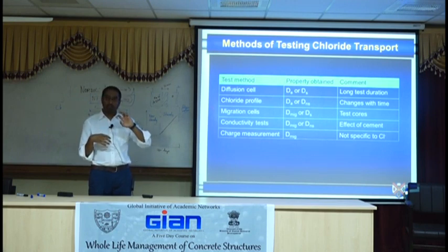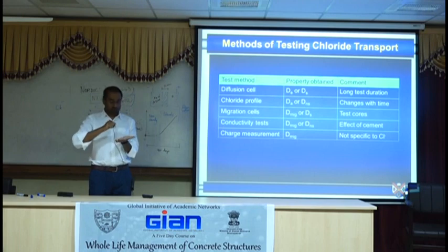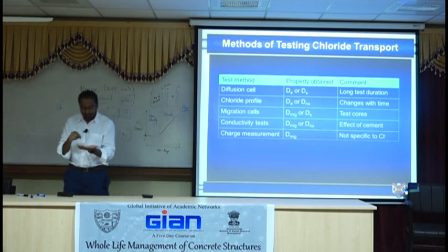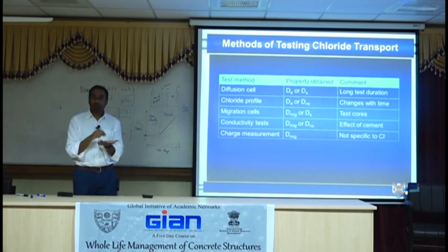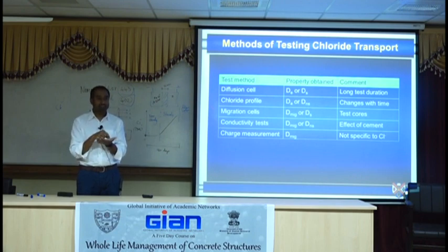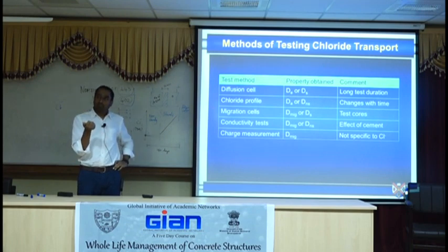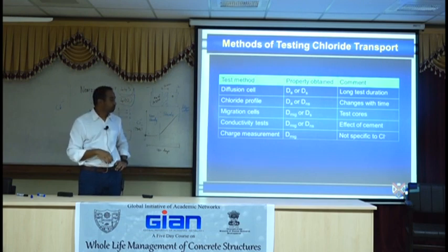Silver nitrate is a very fast oxidizing chemical. Be very careful when you're using your hand with it. It's the same stuff that you have in henna, you know, the drawings that you guys make. Most of the commercial ones that you buy, which is not really henna, actually has silver nitrate in it. It gives you an etching on the hand. The advantage of silver nitrate is it'll react with chloride readily and convert into silver chloride, which is white precipitate. That's what you can see.